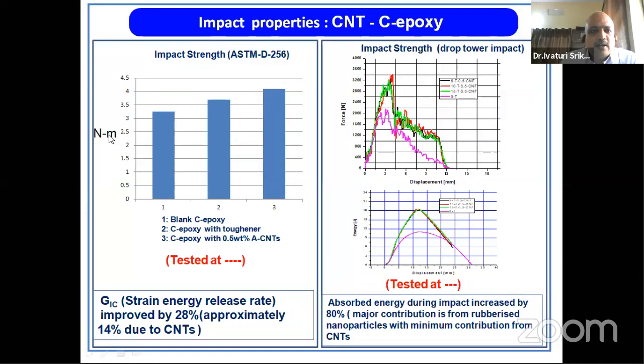Then we have done the impact studies with a drop-weight impact tester. You can see here, this is the force versus displacement. A normal material fails at low force, whereas the nanomaterial added ones, carbon nanotube added ones, show very good improvement in the impact resistance.